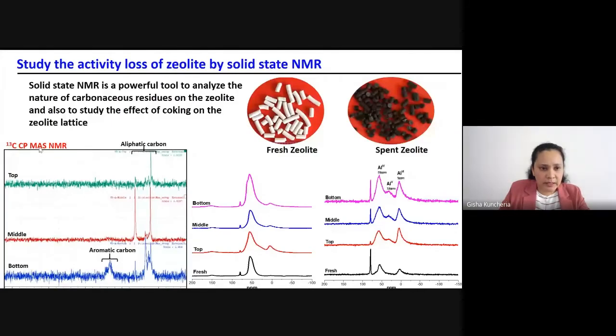So this is a solid state NMR of C13. From the C13, it is very clear this black is from the coke. And among the coke, it contains aliphatic carbon and aromatic carbon also. Again, this is an aluminum NMR. Aluminum NMR tells whether any framework changes happened on the zeolite. You can see here there is only one peak that corresponds to the framework zeolite, and here there are two peaks. The first one corresponds to extra framework. That means some defects are created in the aluminum structure. Silicon NMR also we used to find out the changes.